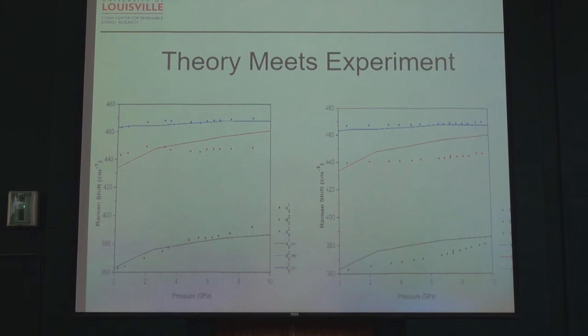Minu's calculation was on black phosphorus. So we can see that the results match very closely for this multilayer sample. This is the theoretical result, the solid line, and this is the experimental result. But if you go to the monolayer sample, the theory doesn't fit very well. The theory is done for bulk sample. Now she is trying to do it for a few layers. This is very encouraging. We are writing a paper on this, with the experiment and the theory coming together.